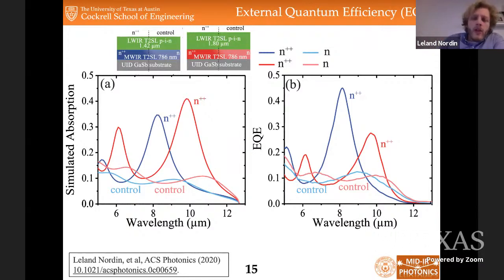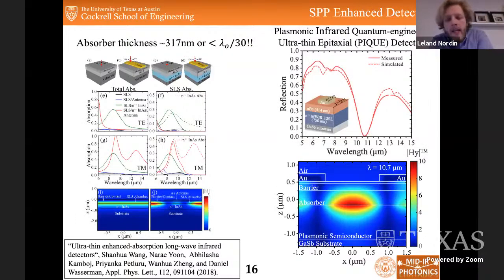So at the beginning of this talk, though, I talked about these SPP modes or these LSP modes, and I've really only shown phenomena leveraging the high reflectivity of the doped semiconductor. So there's a way that we can actually couple to surface plasmon polaritons. Well, in 2018, our group had a theory paper doing just that, where we would have an optoelectronic device grown on top of one of these highly doped semiconductors, and then an antenna, which is actually a gradient coupler to provide the momentum to couple into that surface plasmon polariton mode.